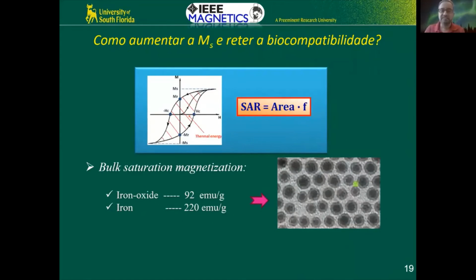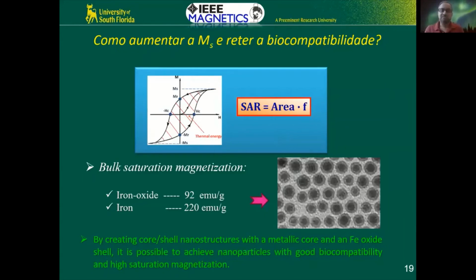And here is something from our lab. You can see they're beautiful core shell nanoparticles. The darker one inside is the iron. The lighter shell is the iron oxide. And we thought we can fool the cells because clearly iron oxide is biocompatible. So the cell will think that it is biocompatible, no problem. But inside we have the iron, which has a larger saturation magnetization. So we did this experiment, and initially we were successful. We were very happy. However, our happiness was short-lived. Okay, I'll tell you the story before moving on to the anisotropy stories.